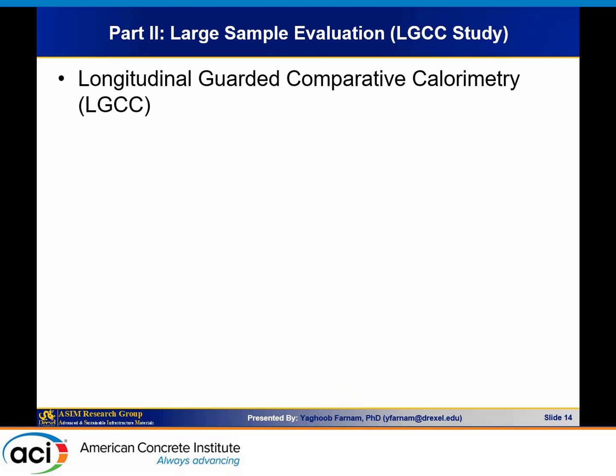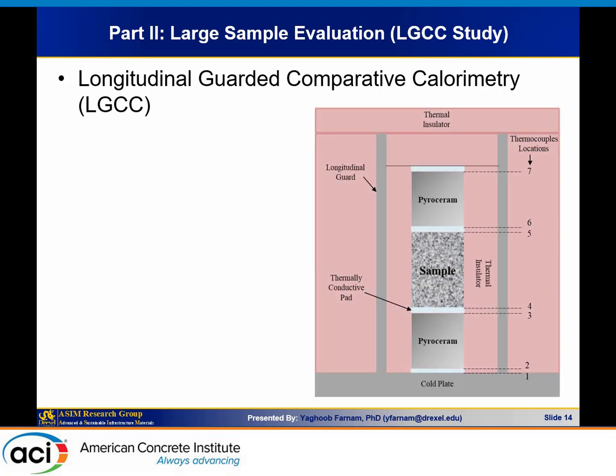So DSC is perfect. It's a very sensitive device, and it's really good, right? But we're not dealing with 15 to 20 milligrams of sample. We're dealing with larger scale, inches of sample. So we wanted to see what would be the performance if we scale it up to something like inches. And that is when we started making a special type of calorimetry in our lab. And we called it longitudinal guarded comparative calorimetry, or LGCC.